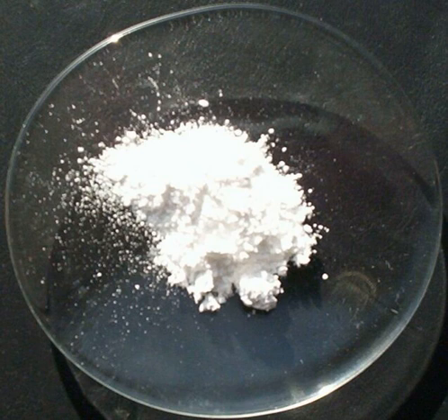Production. Magnesium oxide is produced by the calcination of magnesium carbonate or magnesium hydroxide. The latter is obtained by the treatment of magnesium chloride solutions, typically seawater, with lime. Mg2+ + calcium hydroxide → magnesium hydroxide + Ca2+. Calcining at different temperatures produces magnesium oxide of different reactivity.